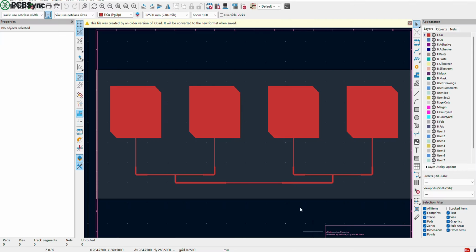Compared to general purpose high frequency materials, a very important feature of RO4534 is its low PIM. In antenna applications, PIM stands for Passive Intermodulation. When multiple high-power RF signals pass through connectors, copper foil, surface treatments, or other non-linear contact points, new intermodulation signals may be generated. If these spurious signals fall into the receiving frequency band, they will affect the system's sensitivity. Rogers' product page also lists the typical PIM value for RO4534 as minus 157 dBc. However, PIM is not determined solely by the substrate. Factors such as copper foil type, current density, etching quality, surface treatment, and circuit cleanliness all affect the final result.